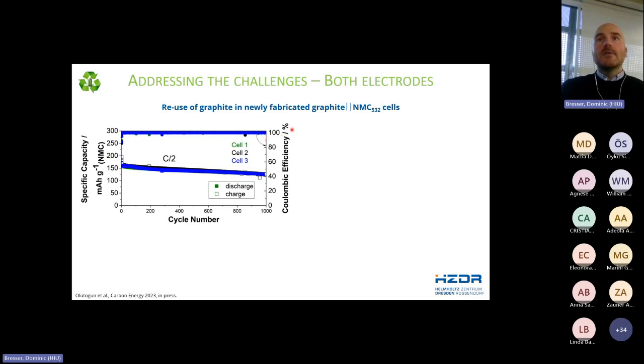And so we did a couple of comprehensive investigations. I will just show the results for the full cells here. So, combined with an NMC 532, so 50% nickel, 30% manganese, 20% cobalt, as active material for the positive electrode. You can see that those cells, it's 3 times the same combination, just for reproducibility reasons. So these cells are cycling pretty stably for 1,000 cycles and in effect more.